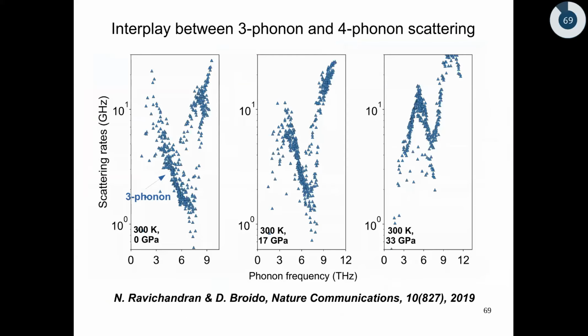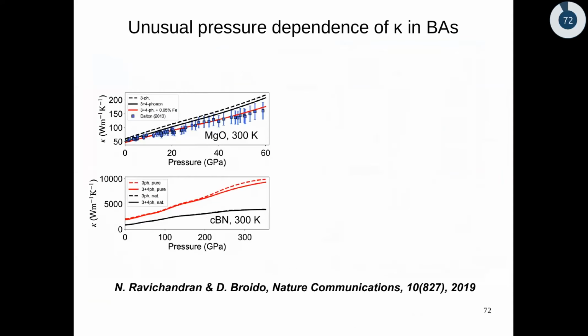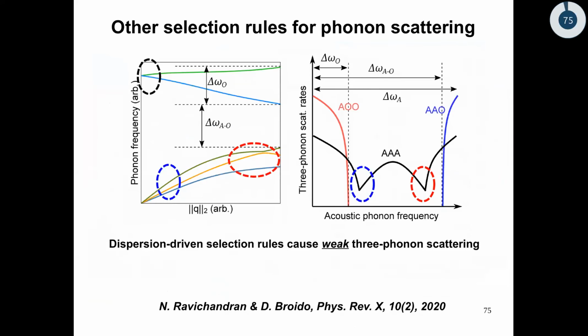It's a very good question. Let me see if I have a backup slide for that. Yeah, so by joint density of states, I'm assuming you mean this phase space, right? The number of... Exactly. Right? So in whichever material we find 4 phonon scattering to be important, there's always a weak 3 phonon scattering phase space. So the lowest order scattering.